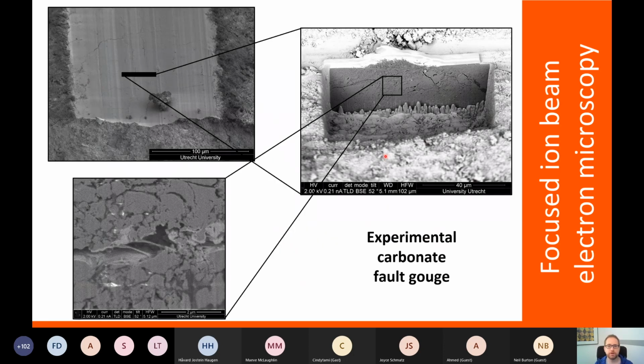So one thing you can do with the focused ion beam scanning electron microscope is to do simple cross-sectioning. Here on the left-hand side, you see an image of an experimental sample. It's calcite, so calcium carbonate, that somebody has deformed inside a laboratory. So there don't need to be always natural samples. This is an experimental sample, and it produced these very flat surfaces. And the person wanted to understand what's actually happening below the surface going into the sample.